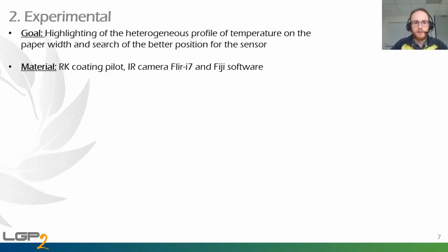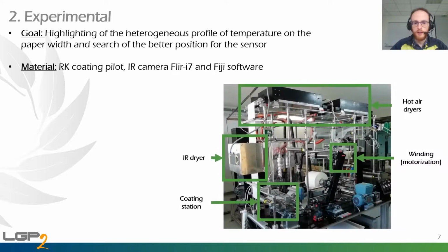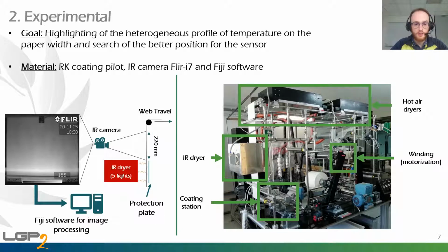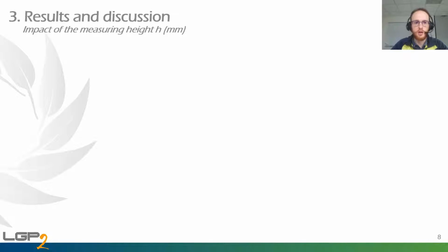Concerning the highlighting of heterogeneous profiles of temperatures in the paper width and search of the best position of the sensors, we're going to do it on the RK coating pilot with an infrared camera and use Fiji software. So here you have the pictures of the coating pilot with a coating station, an infrared dryer, the hot air dryers, and the motorization linked to the winding. This is directly after the infrared dryer that the infrared pictures are taken, and after image processing we will obtain the different temperature profiles.